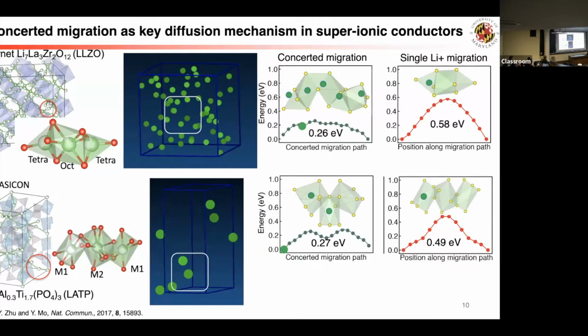Similarly, in this NASICON material, we find this 2-ion jumping-together mechanism gives you a low barrier of 0.27 eV. But if only 1 ion jumps, the barrier is as high as 0.5 eV. So this is actually counterintuitive: when you have 1 ion going through the barrier, it actually has a higher barrier than when multiple of them go through together.